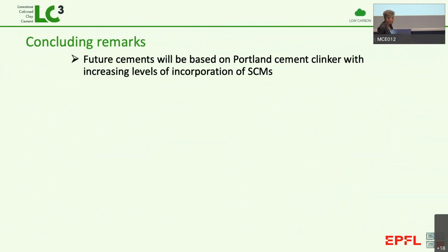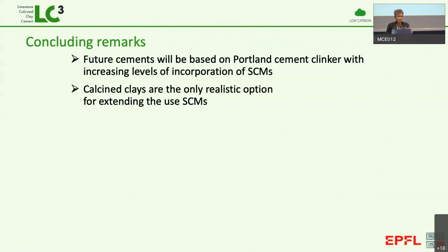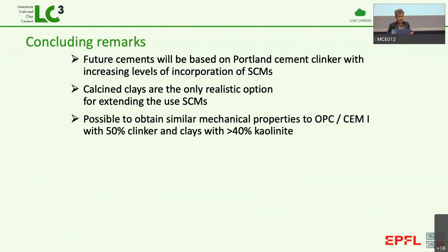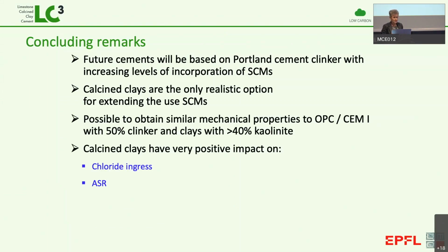So just to summarize that, I hope I've managed to convince you that Portland cements are here to stay, and what we need to do is work on this technology of introducing more supplementary materials. Because of the shortage of slag and fly ash, the only realistic option to do that on a global scale is calcined clay. And we can really get very good properties with only 50% clinker and with clays that have quite a low kaolin content, which can be available as waste.